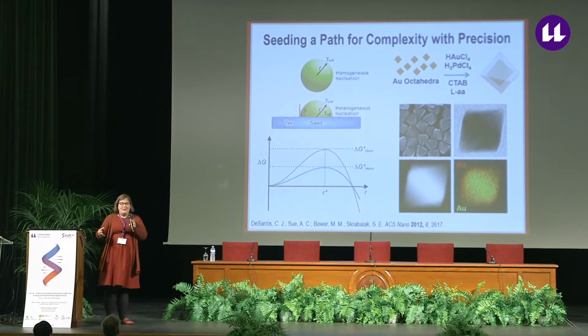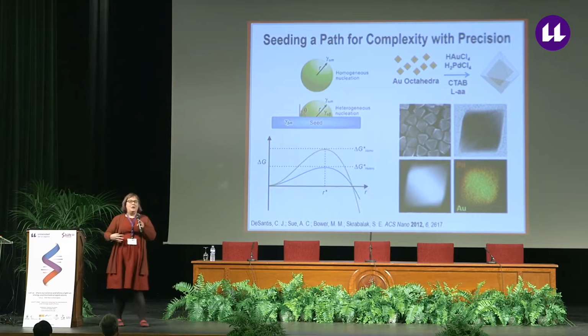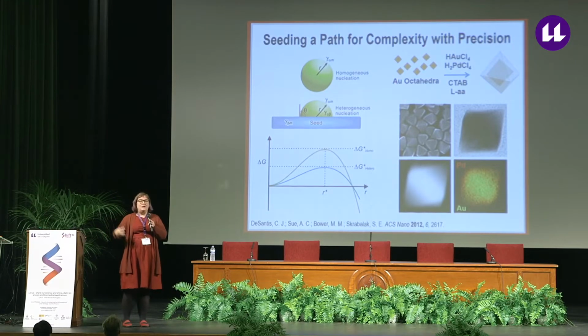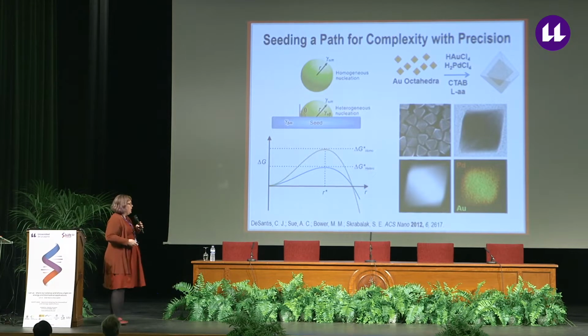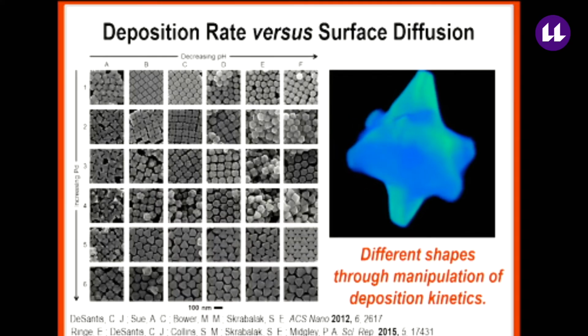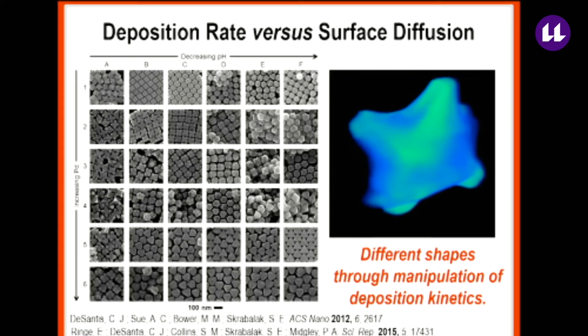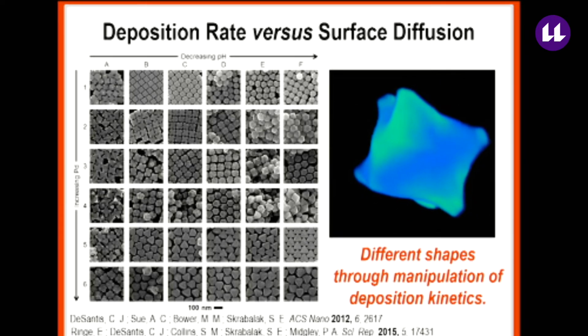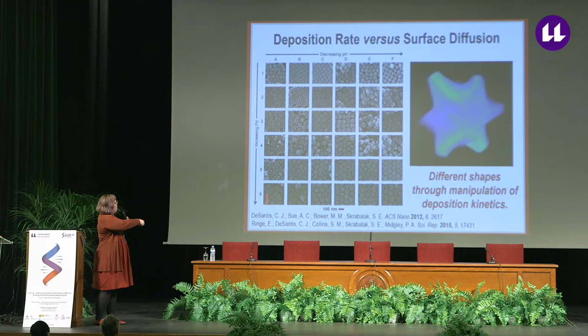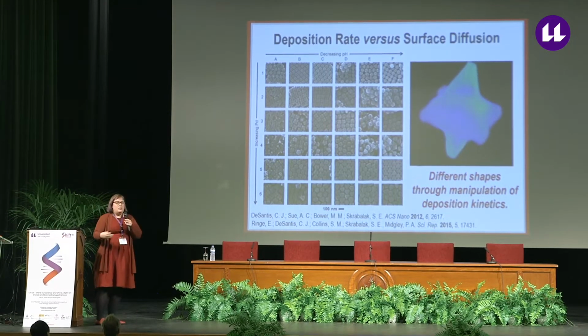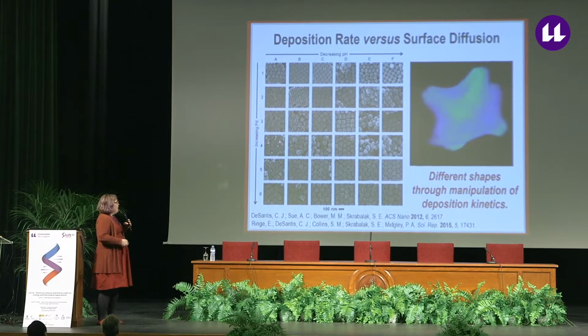So we were really excited about this outcome, that we were able to have a more predictable pathway to shape-controlled alloyed nanocrystals. But it turned out that this synthetic system was quite versatile. And shown here are some of the various types of structures that we could obtain by seed-mediated co-reduction, this exact same synthesis, but just changing the reaction pH across a row, or the overall amount of gold to palladium precursor in that deposition step down a column. And what you can see is that we're able to access a variety of different shapes.